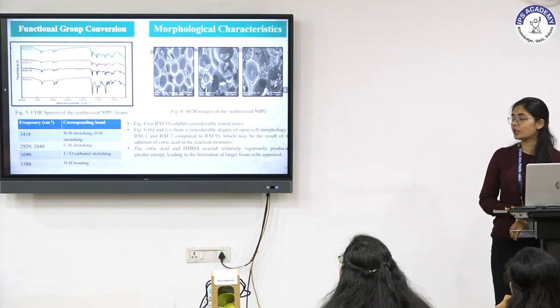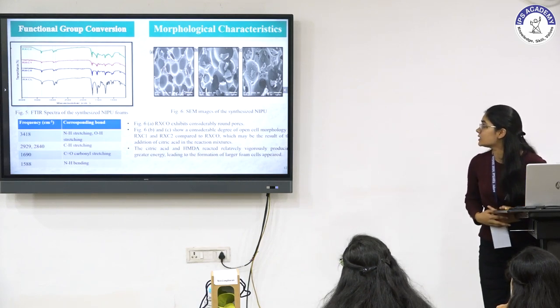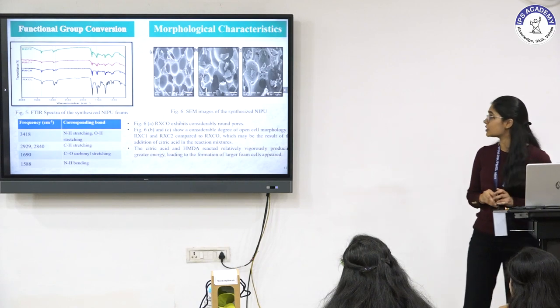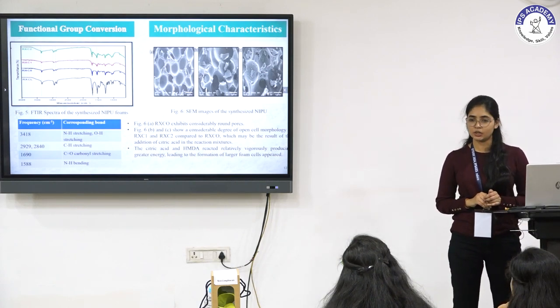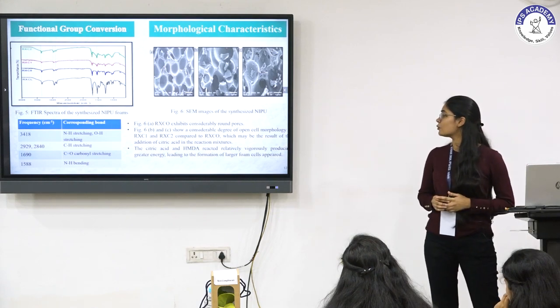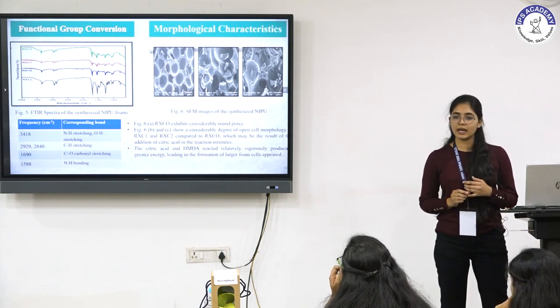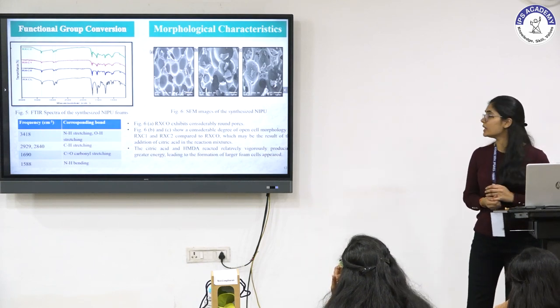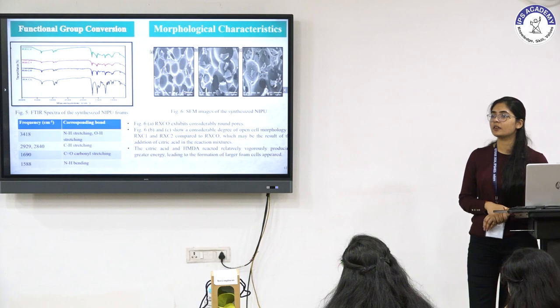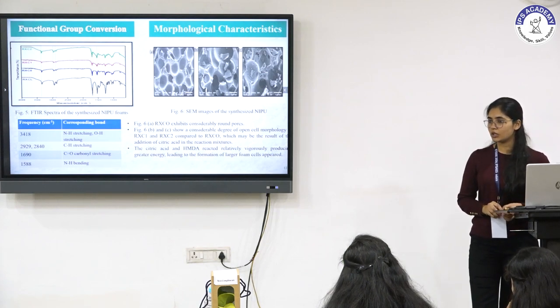The synthesized foam was further characterized using FTIR. RXC0 is the initial reaction mixture, confirming the presence of carbamate linkage throughout the polymeric backbone. Reaction mixtures RXC0, RXC1, and RXC2 contain different amounts of citric acid. The peaks around 3400 cm⁻¹ represent NH and OH stretching due to the OH present in xylose and hexamethylene diamine. The two peaks around 2900 cm⁻¹ are due to sp3 hybridized CH stretching, and the most prominent peak around 1690 cm⁻¹ confirms the formation of the urethane linkage.